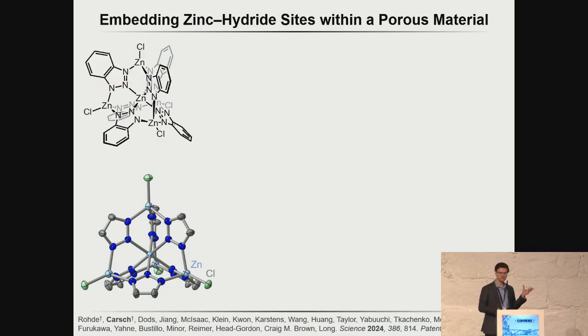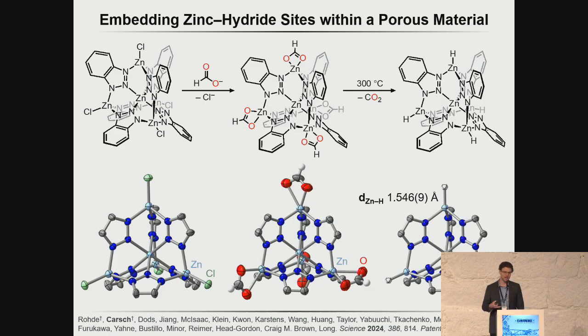And what's really exciting about MFU-4l is that when we zoom into the node, we have this pentanuclear building block, where in each pentanuclear building block, we have these four terminal zinc chloride sites, where we can do synthetic chemistry at those zinc chloride sites and start dialing in electronic structure by changing out the anion or changing out the metal ion. And what we're going to do here is a series of post-synthetic elaborations to change out this chloride for a corresponding hydride ligand through the intermediacy of a formate ligand that can undergo an elevated temperature decarboxylation.